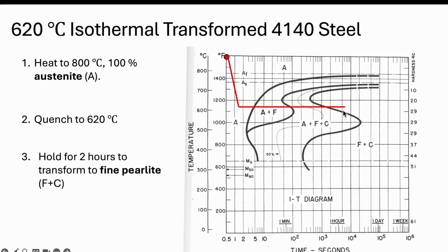And about an hour is good here as well. Or you can do 2 hours to make sure, because you want to make sure you cross and get the whole thing if that's what you want your microstructure to be. And so in this case, we're on kind of the lower end of this C shape. And so we would expect to get ferrite, and our main component is going to be pearlite.